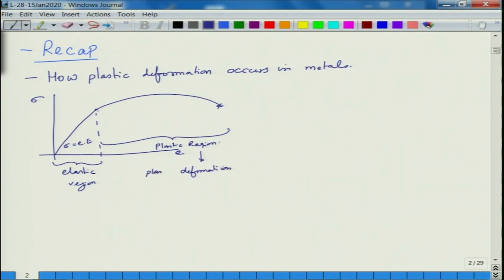and this is the region where the plastic deformation occurs. So, we saw that this point at which your load is maximum or engineering stress is maximum is called UTS. At this point your necking begins. So, up to this point material strain hardens, and beyond this point there is a load reduction after necking, because of excessive reduction in the area at the neck, and then you of course have fracture.